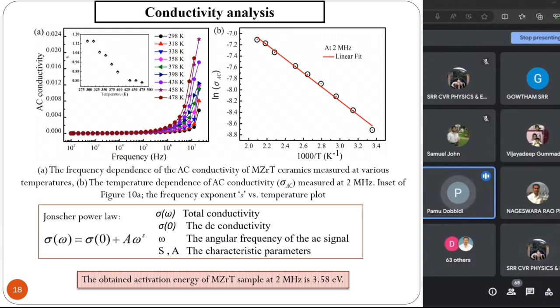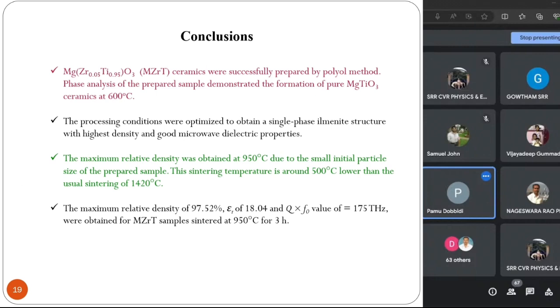What will it indicate? When you have a higher activation energy, it means you will have a very good insulating nature of the material, and it will also reflect the conductivity of the material, which is very small. We want to see why we are doing this AC conductivity, all that, because we want to see how stable is this material, because that is the reason we do all these measurements. Can you go to the next slide, please?